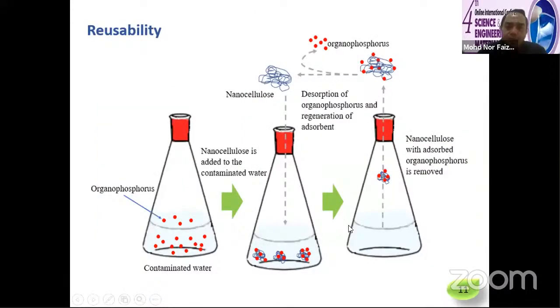Another interesting finding is that the nanocellulose can be reused many times after absorbing organophosphorus. It can simply be seen here. The contaminated water contains organophosphorus, and when we add nanocellulose, it absorbs the organophosphorus, and we can remove the nanocellulose and the organophosphorus. Then we can do the desorption process by simply dissolving this material into methanol or any kind of solvent that can dissolve organophosphorus, and the nanocellulose obtained can be reused again.